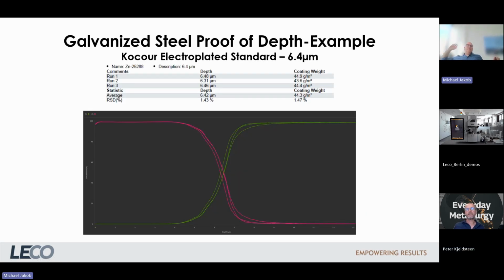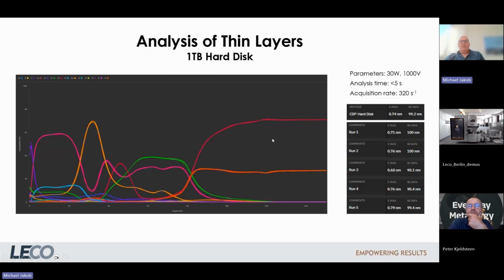Sometimes the question comes how you control that. Well, the LECO machines, and now it goes really into detail, are sputter rate corrected, so we calculate that more or less. But you can, of course, check that, there are some standards available, like this standard, which has a 6.4 micron interlayer between zinc and iron. And of course, we match that quite well with 6.42, RSD plus minus 1%. This is just an example.